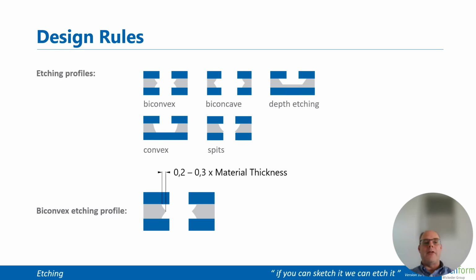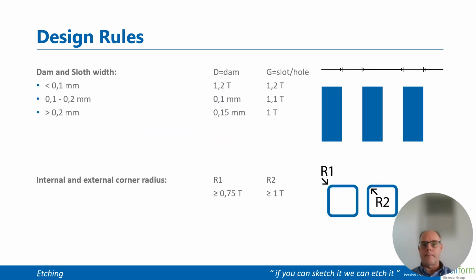If we etch, we get a certain profile, and the biconvex is the standard profile, where the edge is approximately 0.2 to 0.3 times the material thickness. We could get rid of the edge by etching longer, resulting in a biconcave profile. However, a drawback is that the hole gets bigger and bigger. So it has an influence on the minimum hole size that we can etch. Talking about that, the minimum hole size is 1.2 times the material thickness. So we cannot etch holes smaller than the material thickness.